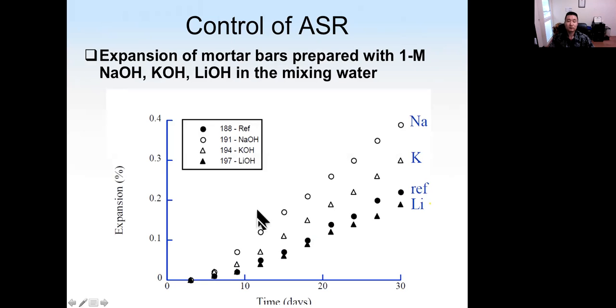Okay. So here shows an example of expansion of mortar bar prepared with 1 molar of sodium hydroxide, potassium hydroxide, or lithium hydroxide. You can see for lithium hydroxide, the expansion value is lower compared with potassium. The reference is the control mix, which has no hydroxide.